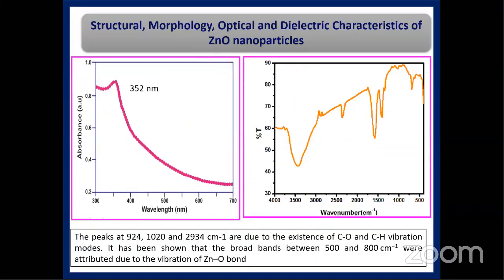The next material is zinc oxide nanostructure. You can see the UV absorption spectrum of the zinc oxide nanostructure. The UV band is observed at 350 nanometers, and this is the FTIR spectrum of the zinc oxide nanoparticle. We can confirm that zinc and oxygen bonding occurs in the 500 to 800 cm⁻¹ range.